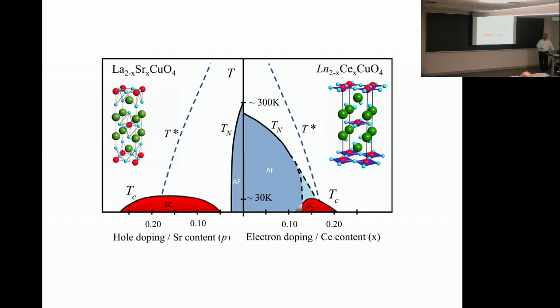So this is the famous phase diagram of the high temperature superconductors as a function of hole and electron doping. You have superconductivity on both sides, and in the middle you have an insulator, which is an antiferromagnet, which extends over different regimes, but much larger antiferromagnetism in electron doping than the hole doping. Anyway, the question that's largely driving our research is trying to understand what happens here at low temperatures in the regime where the Tc is the highest. So this is where you get, in YBCO, this Tc will be much higher than this, up to 90 Kelvin and so on.